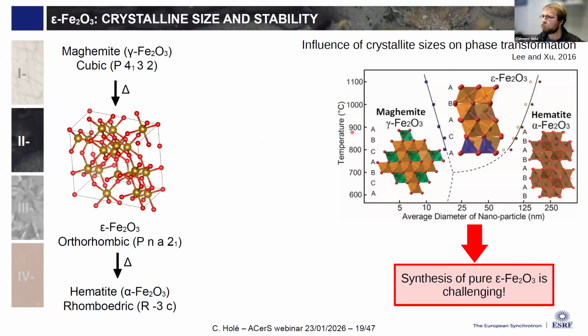However, one of the problems of this phase, especially for people who want to synthesize it and use these very interesting properties, is that it's a phase that is confined in the nanoscale, as can be seen here by this phase diagram by Lee and Xu. Since it can very easily transform into hematite, the synthesis of iron epsilon oxide can be very challenging. But here we get another inconsistency.